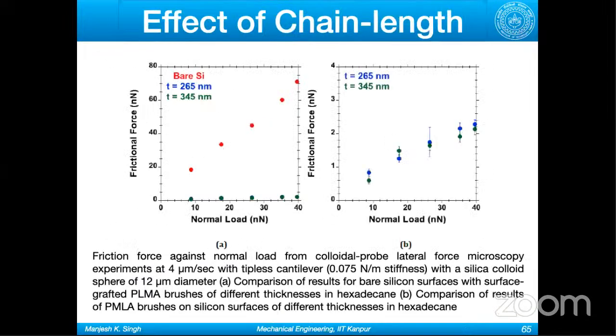With this, I'll move to the effect of chain length, which is something not very clear. So here again, these are my experiments. Bare silica gives you very high friction. As soon as you graft polymer chains on the surfaces, the friction goes down. But there are two curves. In this plot on the left side, you cannot see it, but on the right side you can see it when I zoom in.